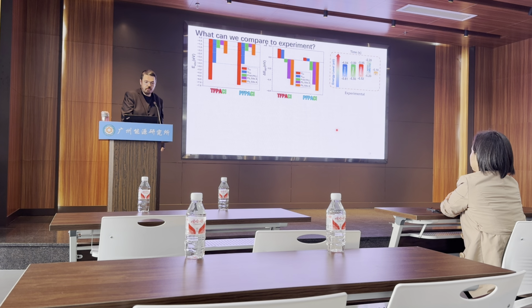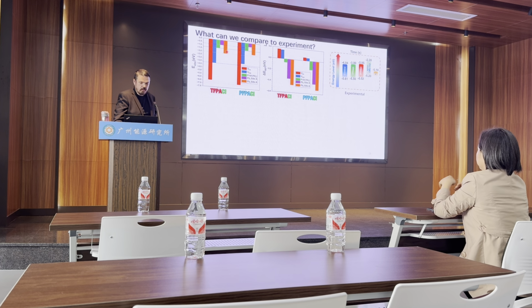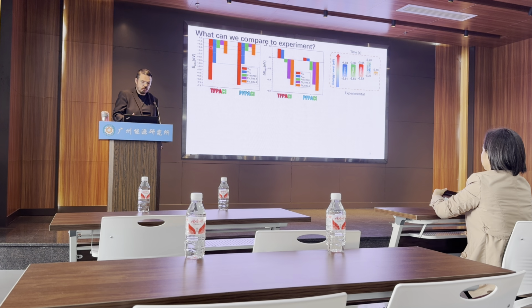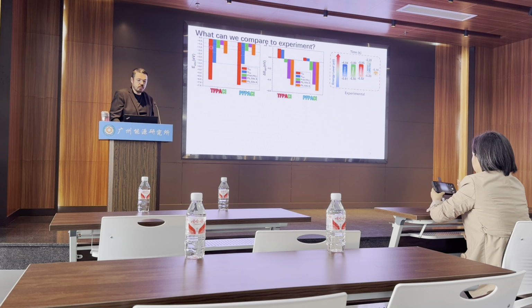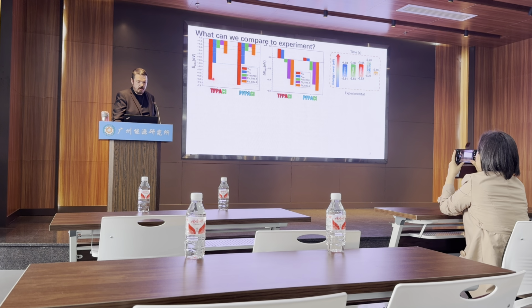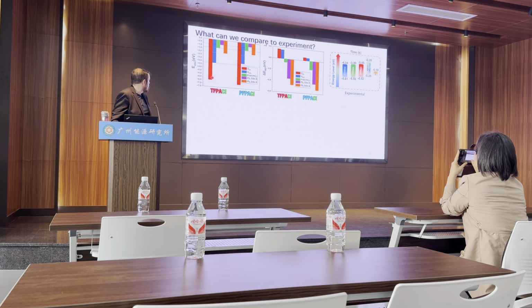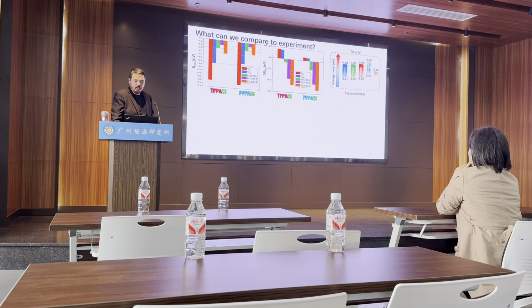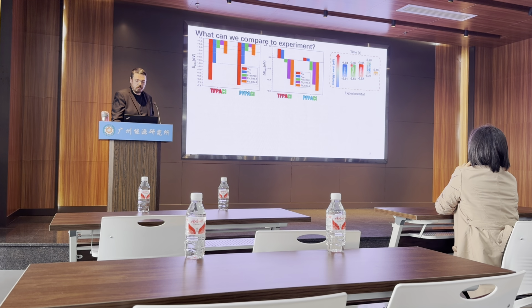So what can we compare to experiments? It's a little bit challenging actually. Here you can see the adsorption energies for all the cases I described before where the charge is reasonable. All the reasonable cases I'm considering vary from nearly -7 eV, so very strong, and in other cases less than 1, so pretty weak. And then we also look at the work function change, and you can see the iodine-rich surface shifts the work function up, and on the other surface it shifts it down. And we know from experiment that it's actually shifted down.